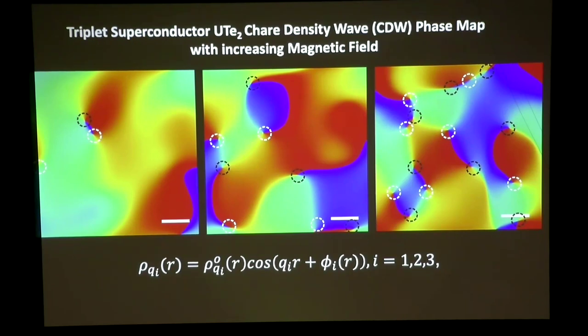What I'm showing you here is the charge density wave in this superconductor called uranium telluride. And what I'm plotting here is the phase slips. Each point here is a position where the charge density wave actually has a phase slip, where the phase has a finite value. And the way the charge density wave gets destroyed, in fact, this CDW gets destroyed with a magnetic field, which is very strange, is by creating more and more phase slips. That's what these images are telling.